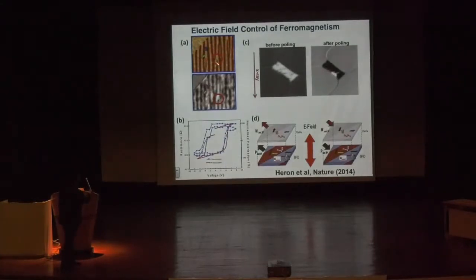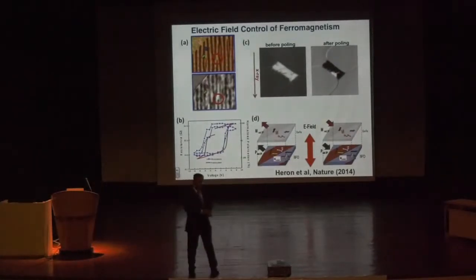Okay? On the top left, you have the ferroelectric domains. Those are the stripy things we talked about. Those are 71-degree rotated domains. The corresponding magnetic domains of a ferromagnet, in this case a piece of cobalt iron, is shown in this image. Again, it's a photoemission electron microscope image using circularly polarized light, which is sensitive to ferromagnetism. Okay. You could see these two guys look exactly the same. So the first thing that the postdoc concluded was, oh, look, the ferroelectricity is controlling the magnetism. Absolutely not. They don't talk to each other. It turns out that the canting moment in the bismuth ferrite is mapping exactly the same way in these domains, and so it was just accidental. So the ferromagnet, the cobalt iron, was coupling to the canting moment.